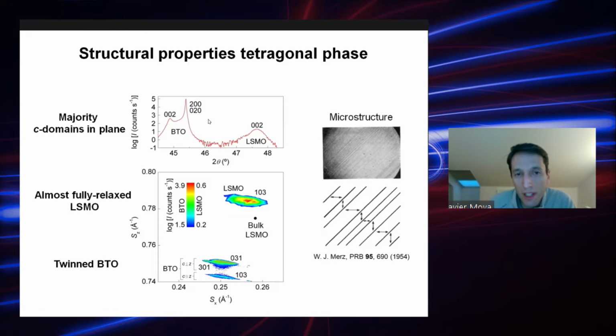And you can see from these peaks that there is a majority of C domains in plane, because you see this peak, which corresponds to the c-axis in plane, has much higher intensity in the X-rays. So what we know from the X-rays is that we can expect a microstructure that looks a bit like this.